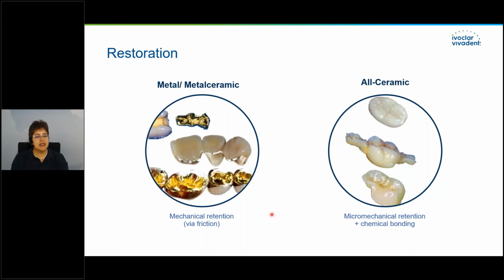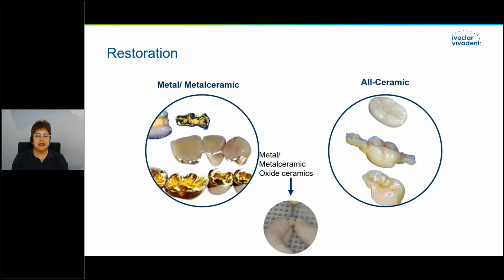In the case of the metal and metal ceramic restoration, we will have, as I explained you already, the friction. And for the fancy all ceramics restoration, we will need micromechanical retention plus a chemical bonding. For the roughening, we have two main procedures: sandblasting and etching with hydrofluoric acid. Sandblasting is done basically in the lab for metal and metal ceramics restoration or oxide ceramics like zirconia. And for the glass ceramics or lithium disilicate, we use hydrofluoric acid.